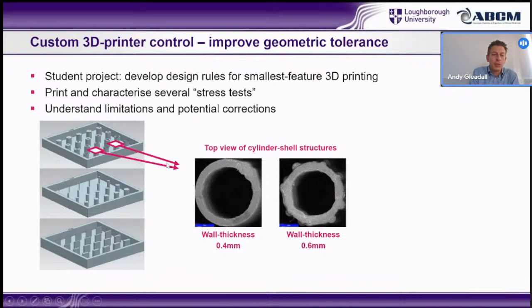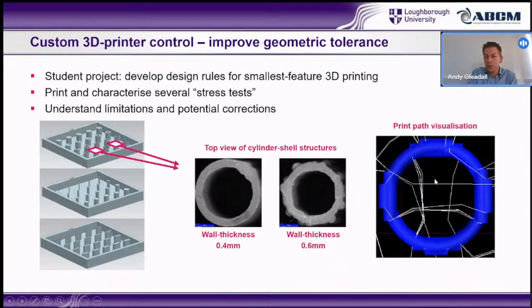And depending on the wall thickness, if the wall thickness was set to exactly the same size as the nozzle, we got this nice round circle. If it was set a bit wider, we got this real weird mess. And looking at the toolpath, it looked like this. It was printing a circle, and then because it was supposed to have printed 0.6 millimeters wide, and the first circle was only 0.4, it then thought, I've still got to put in 50% more material. So it just dumps it in this reasonably symmetrical manner.